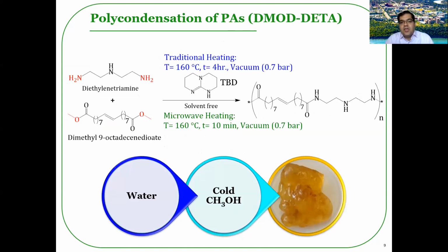To produce the linear polyamides DMOD-DETA, Dimethyl 9-octadecenedioate was polycondensed with a linear triamine called diethylenetriamine through one-step heating process at 160 degrees centigrade under vacuum. Fortunately, the microwave polycondensation reduced the time of the reaction from 4 hours to less than 10 minutes. The product of the reaction was floated in water, and then the polyamides was washed with both water and cold methanol to produce this yellow to brown polyamide.